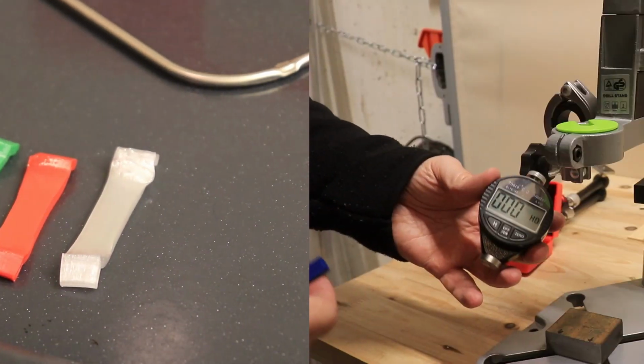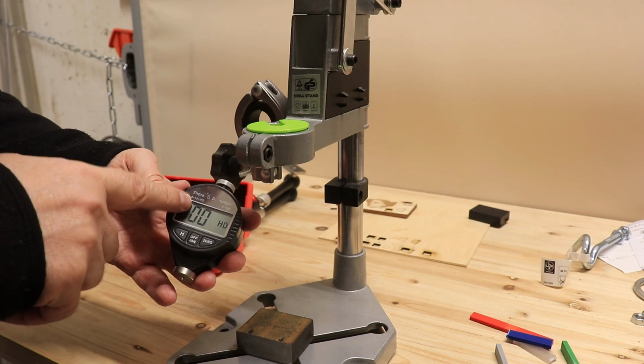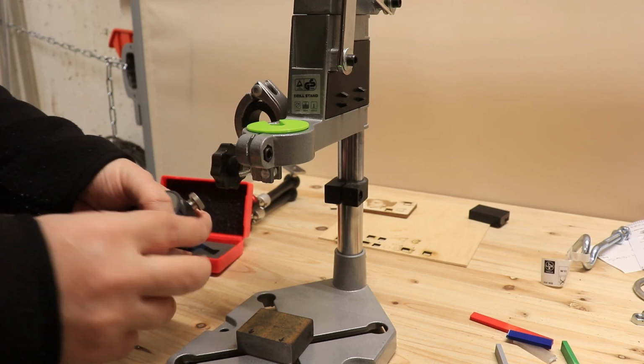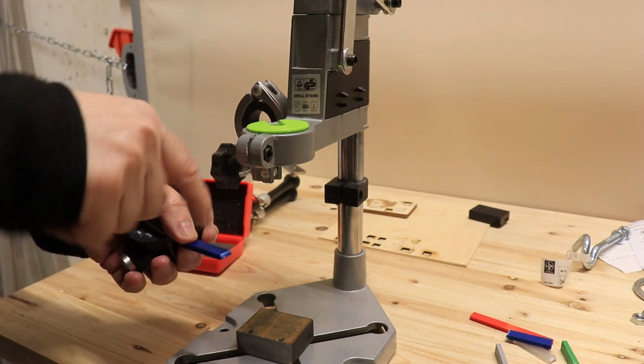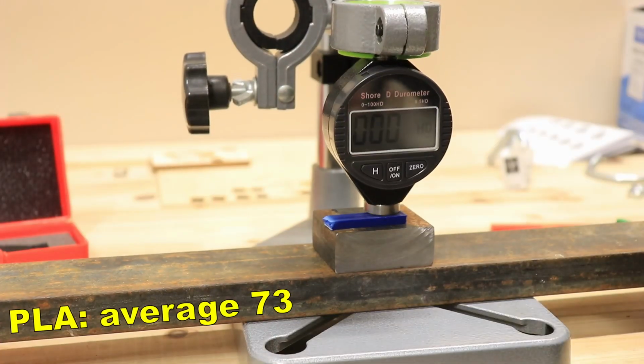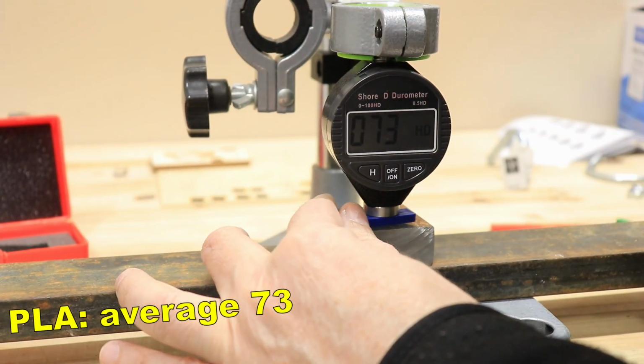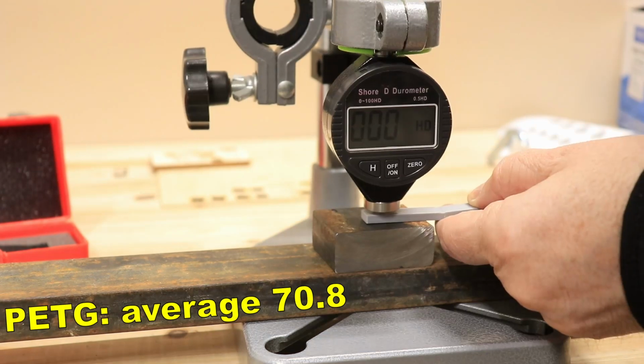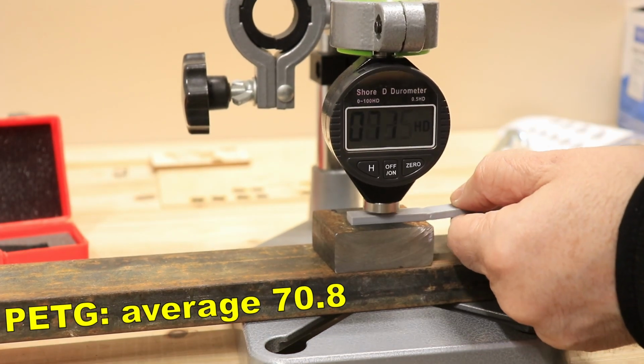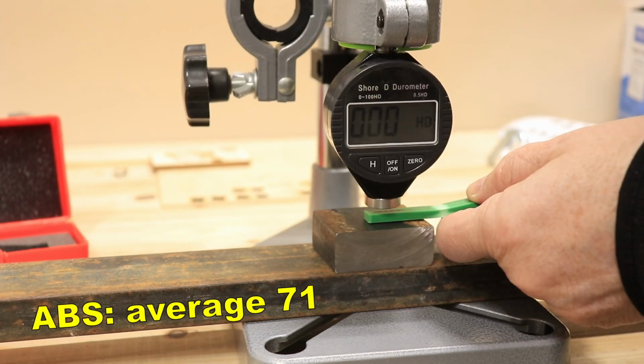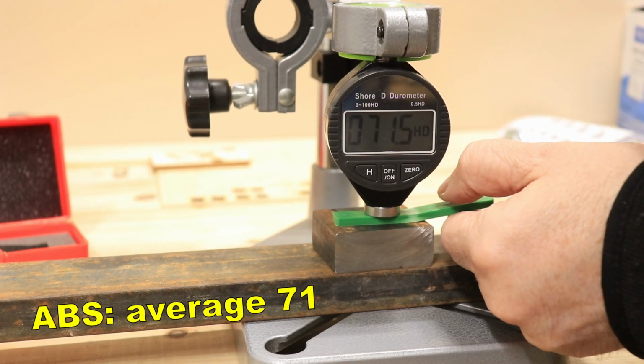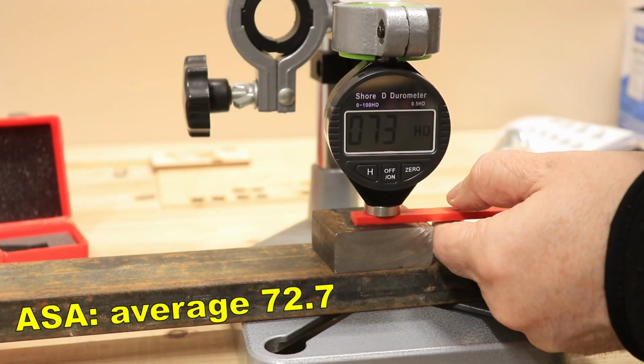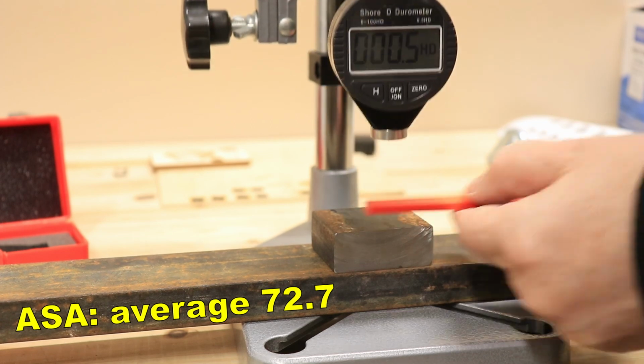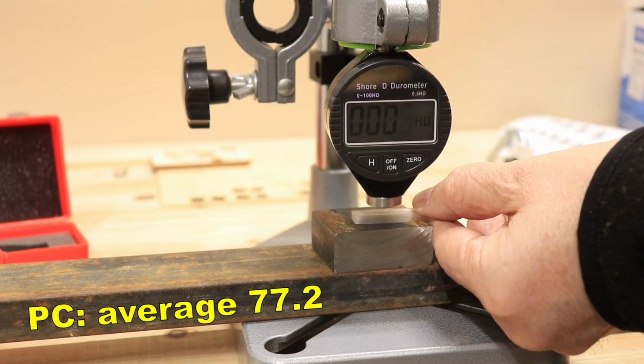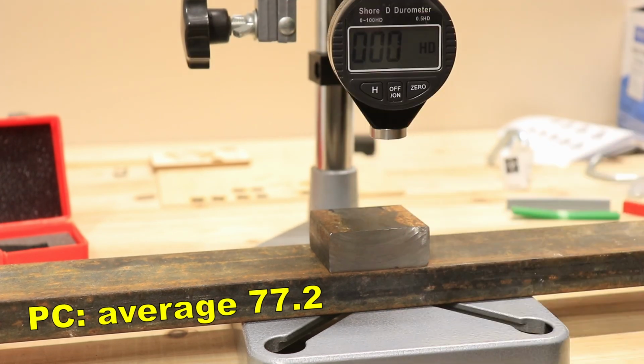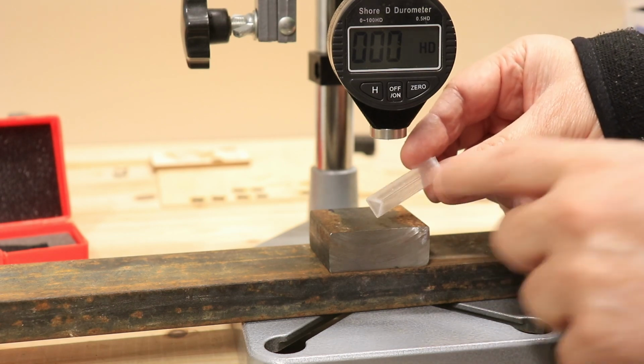this test. And now let's measure the hardness with this Shore D durometer, and I will measure it perpendicular to the layers. PLA 70.5, 70, 70.5. PETG 71, 71, 70.5. ABS 71, 71.5, 71.5. ASA 73, 73, 72. Polycarbonate 76.5, 78, 77. So from these 5, the hardest is the polycarbonate.